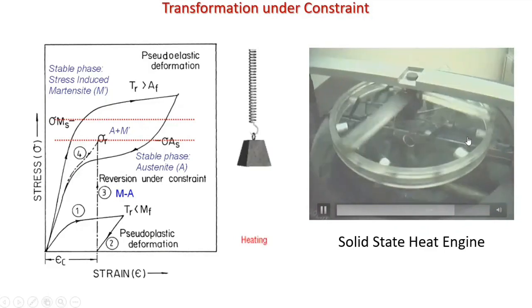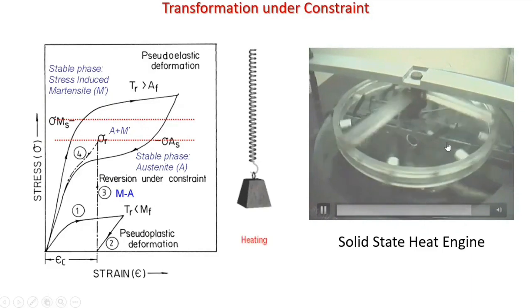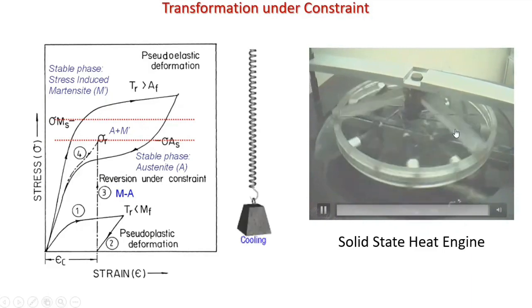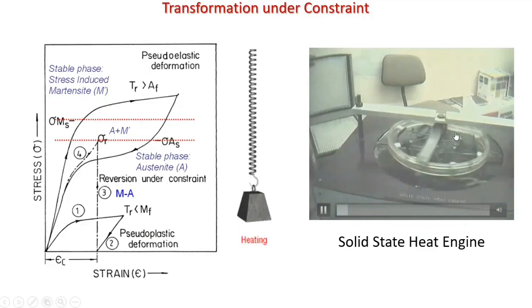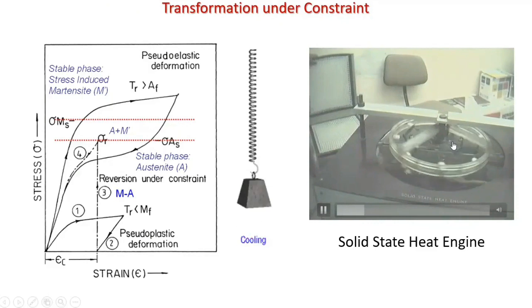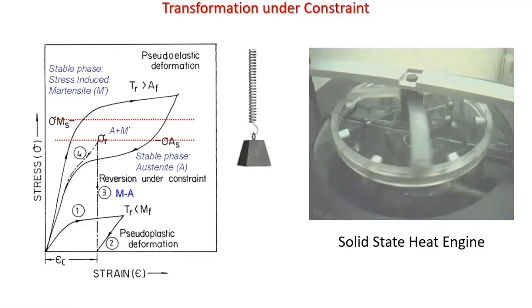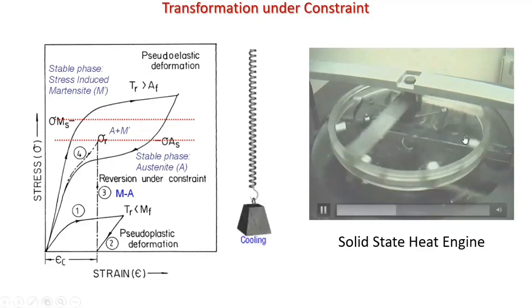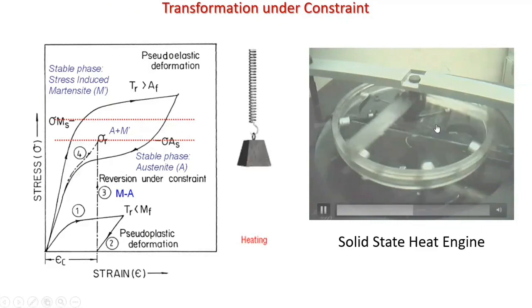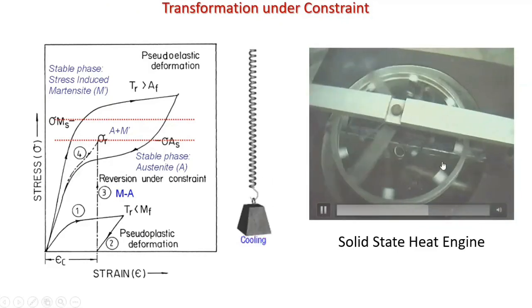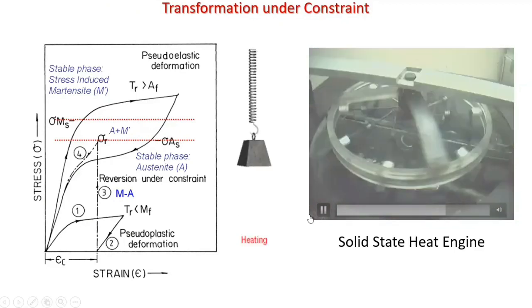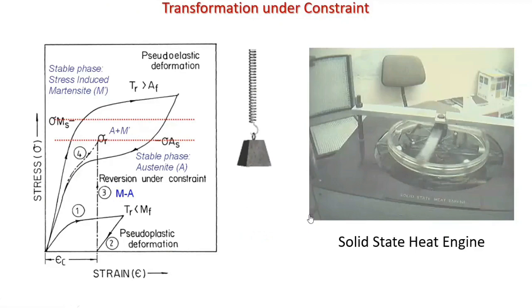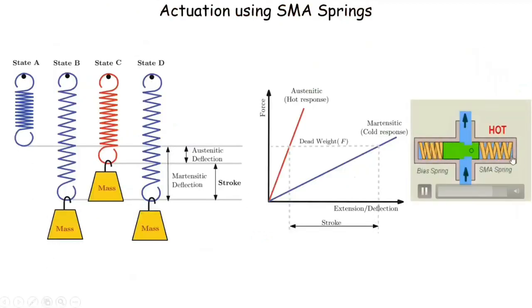So there is quite a good efficiency, and the efficiency is even better if you think that this difference of temperature was 30 degrees. Now this 30 could be minus 80 and minus 50 also, and that's startling. If you consider that it's minus 50 and minus 80, you can never think of another system that can do this. That's what phase transformation does. And this is not the only example of phase transformation giving out heat, giving out energy. I think there are a lot of examples. This is one example where a phase transformation, or a phase change system, as they call it nowadays, is actually driving this. So this too is an actuator. You have many such actuators which are moving this thing around, because it's all connected to a single crank.